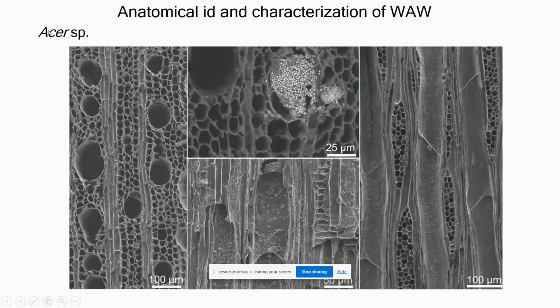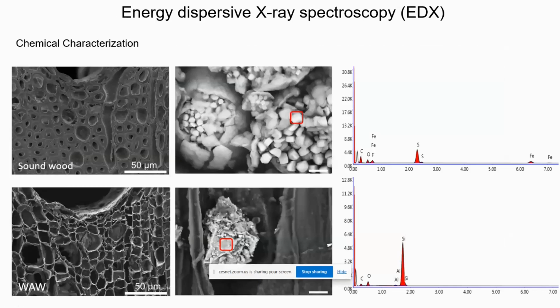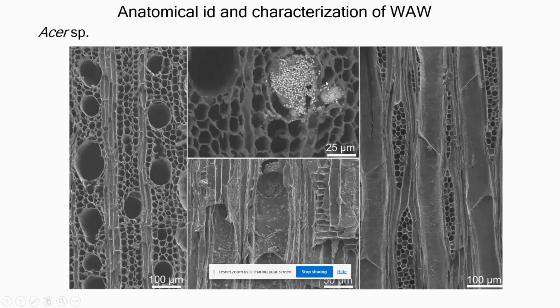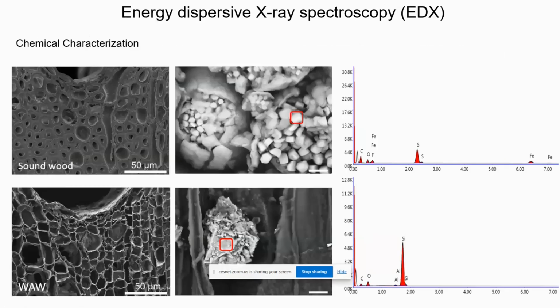In this case, we identified Acer species, and also got some insight and saw some details that are usually hard to see, like here in the vessel, these helical thickenings, and also the position of those bacteria. We also applied, together with SEM, energy dispersive X-ray spectroscopy, EDAX, for the chemical characterization. As you saw before in the vessel, there are some crystals that we found, and we wanted to identify the elements that were inside to understand which kind of crystals they were.